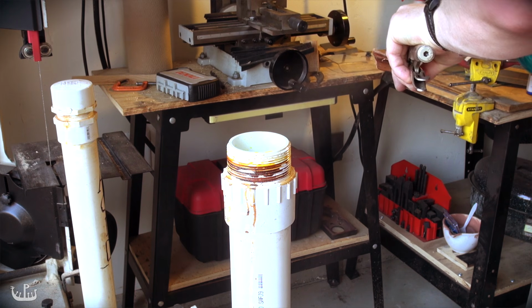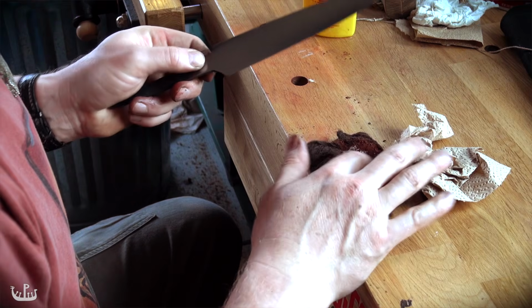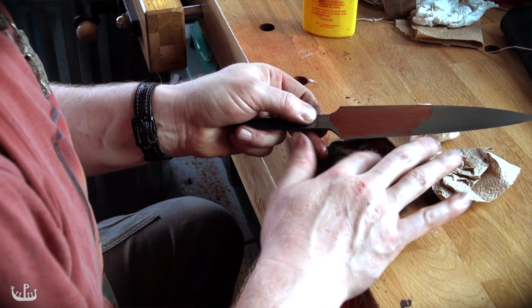To achieve a very subtle look, I remove most of the black oxides using 1000 grit sandpaper. Afterwards, I mix red iron oxide with oil and rub down the blade. This creates a somewhat matte finish.